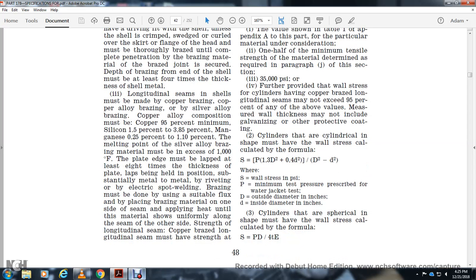Longitudinal seams of shell must be made with copper brazing with the copper alloy, brazing silver alloy, brazing copper alloy composition: copper 95% minimum, silicon 1.5% to 3.85%, manganese a quarter percent to 1.10%. The melting point of the silver alloy brazing material must exceed 1,000 degrees Fahrenheit. The plate edge must be lapped at least 8 times the thickness of the plate, with the lap held in position substantially metal to metal by rivet or electrical spot welding.